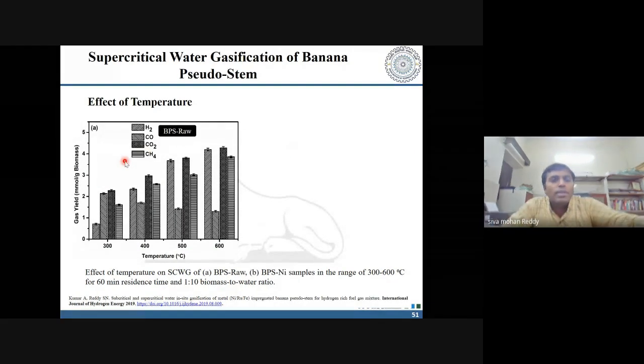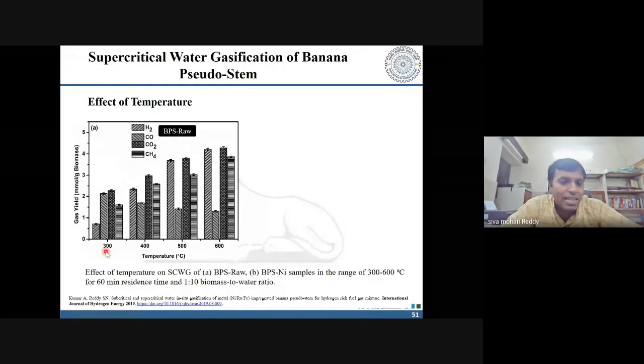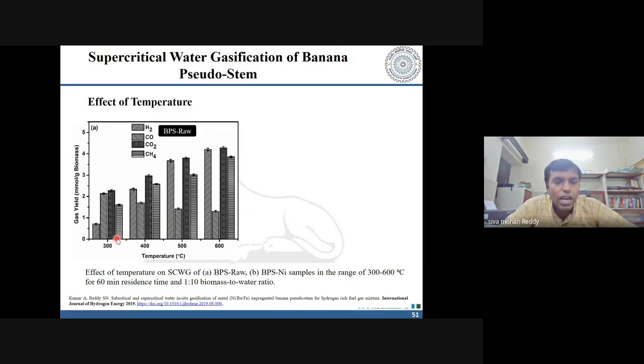Okay, so now the same thing has been mentioned. If you look at the individual gas yields that have been formed at 300 degrees centigrade and 600 degrees centigrade, you see that the hydrogen gas yield, which is very low at 300 degrees centigrade, has significantly increased when you are increasing the temperature from 300 to 600 degrees centigrade. The reason why the hydrogen gas yield significantly increases is because of 2 reasons. One is your water gas shift reaction, other is your cracking and reforming reaction.